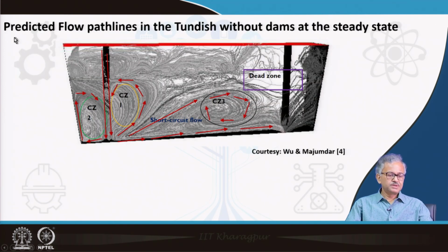Now this is very important: the predicted flow path lines in the tundish without dams at steady state. You have a tundish and the liquid stream is coming in and hitting at this point, and you don't have any pad there. So there is no turbulence arrestor here, and huge turbulence is created. You can find two mixed zones created around this liquid stream in the tundish.